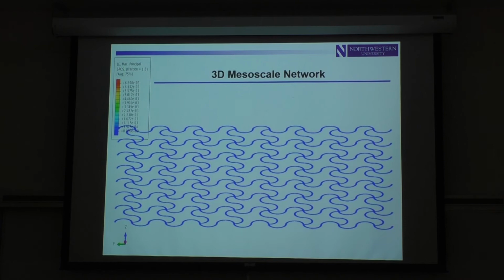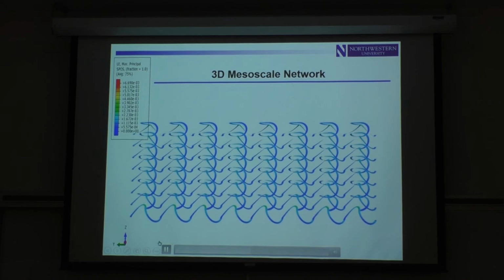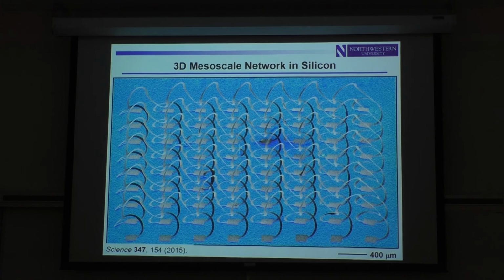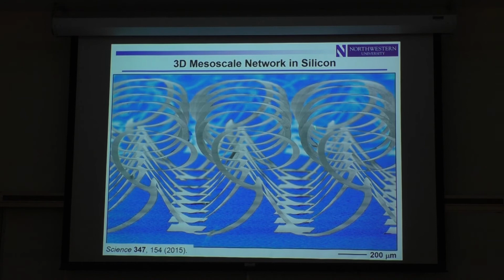You can do all kinds of things. This is a sort of two-level structure that consists, upon geometric transformation, of a series of coils that are going in one direction, and then another series of coils sitting on top of the first, oriented in the orthogonal direction. And you'll see this transformation here, bonding sites down here, obviously. And then that's a kind of 3D construct you can generate. That's, again, silicon on silicone. This is a cross-sectional view. You see the three-dimensionality of these systems. Again, device-grade silicon. It's easy to integrate any kind of device functionality you want on top of that.